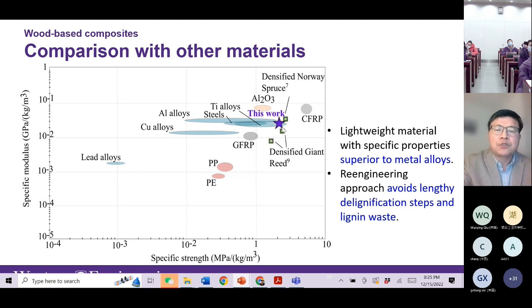Our new material has a much higher specific strength than any other metals. And because of the lighter weight, it is more superior to the metal alloys. It's stronger and also lighter. So now we achieved our target with the re-engineering approach: we obtained a highly strong and lighter material, and our process is better than the literature process. We do not have a lengthy delignification step, and we do not need to do densification for a long time. Our time is only minutes, compared to 24 hours in the literature. This makes the process more advantageous than the current state of the art.